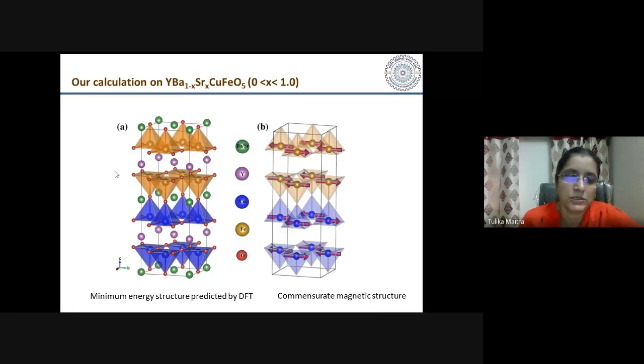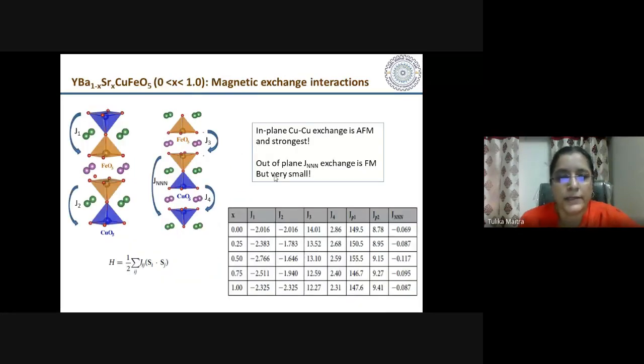Okay, so we considered this structure where there are bilayers of iron and copper, and this is the commensurate magnetic structure that was found to be lowest in energy from the density functional theory calculations, where the spins are in the plane, and it's antiferromagnetically ordered. So now the next job is to calculate various exchange interactions. So we calculated various exchange interactions.